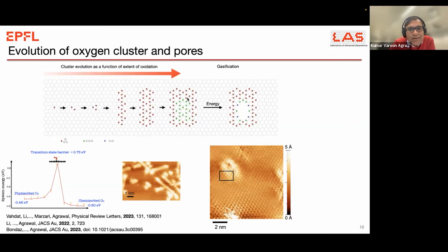These chains then organize. If you increase the density or continue the reaction, they make a bigger cluster. So you can now see bigger clusters. And if you provide energy to these clusters, then the central part of the cluster, which is much more reactive, will gasify, leaving a hole. This became a very interesting technique for us because we could prepare all of this, from this step to this step, in a very uniform way without preparing a hole, and then we can decide when to open the hole.